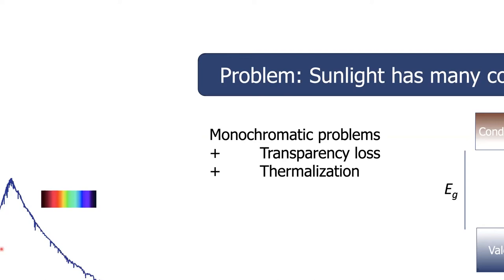So if we have a lower energy photon compared to the absorption edge, the band gap of our material, then we just can't absorb it. We're not having any nonlinear optical processes. This is not a high harmonic generation kind of thing. This is just in linear absorption. We can't absorb these photons. And so that's a loss. So that says we want to have a small band gap in order to absorb a lot of these photons.